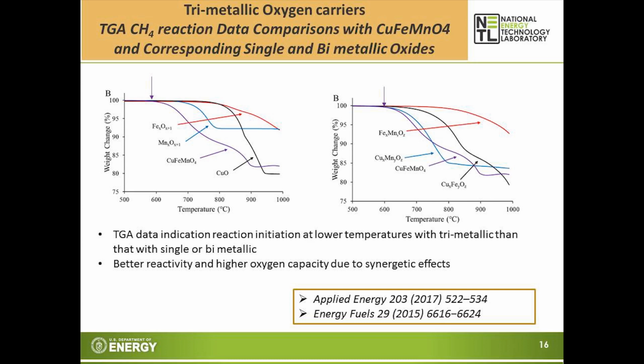We saw similar behavior when we compared with the bimetallics. Again, the trimetallic initiates the reaction with methane at a lower temperature. So this again indicates there's a synergetic effect due to having the three metals together, and the copper seems to again enhance the deeper reduction of iron and manganese. And we saw better reactivity and oxygen capacity due to these synergetic effects.